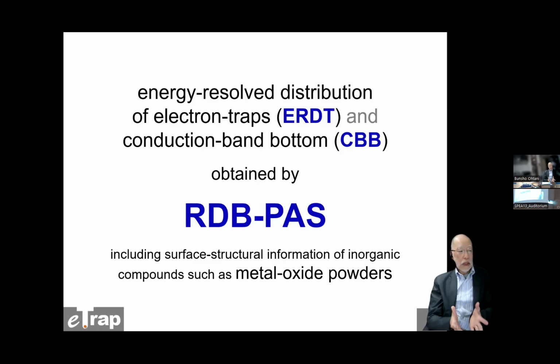So then, about 10 years ago, we proposed that the ERDT-CBB pattern can be information including the macroscopic surface structure. And if we can use this, no other analytical data is necessary. So what is ERDT? That is energy-resolved distribution of electron traps. And the CBB is conduction band bottom. All these are energy distributions. And those data can be obtained by RDB-PAS. So before the interpretation of RDB-PAS, I will tell you about what electron traps are.